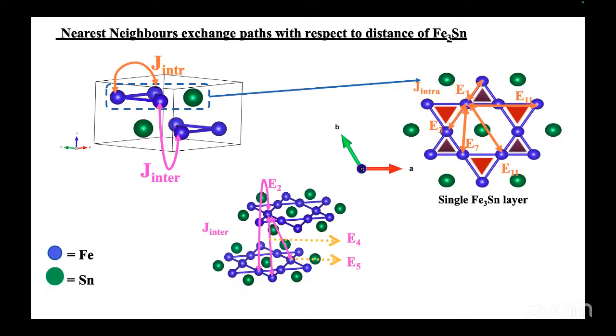So this is showing the exchange path that I have taken for the first nearest neighbor interaction, which, according to the distance, is in-plane, that is E1. And the second, according to the distance, is the E2 path, which is an interlayer interaction. And then we have E3, which is again my intraplanar interaction, and so on and so forth. For the fourth, we see an interlayer interaction between the two layers of the Kagome, and E4 is also an interlayer interaction. And with respect to distance, this is how I calculated the Jij.